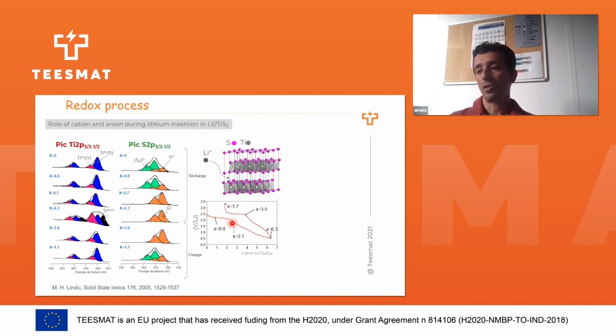And this is our galvanostatic discharge and charge curve. What we did, we cycled our coin cell and stopped it at different cutoff voltages. We opened the cell in the glove box, as I explained before, transferred it to the XPS, and acquired XPS spectra at different voltages. Since we have titanium and sulfide, we will probe both atoms, the titanium core peak and the sulfur core peak. This is the starting point without any insertion. Before insertion, we can see that we have two oxidation states of titanium and two oxidation states of sulfur. We have sulfide S2- and disulfide S2 2-.